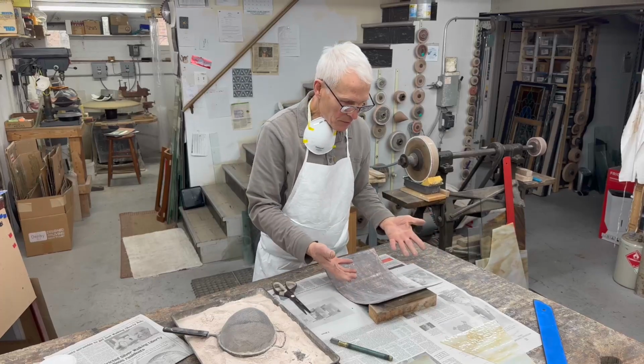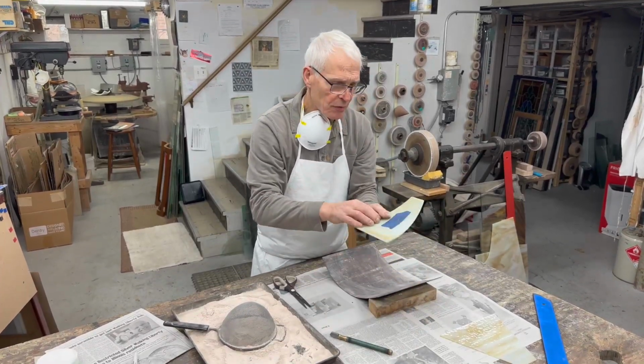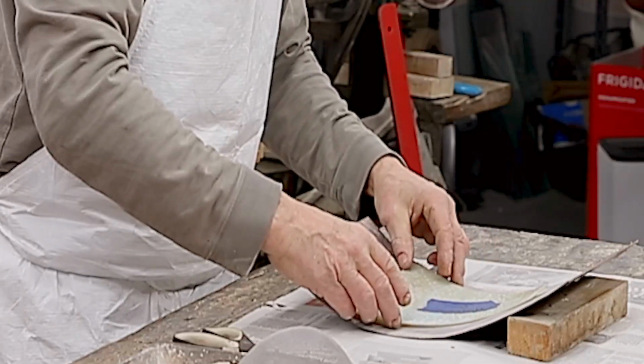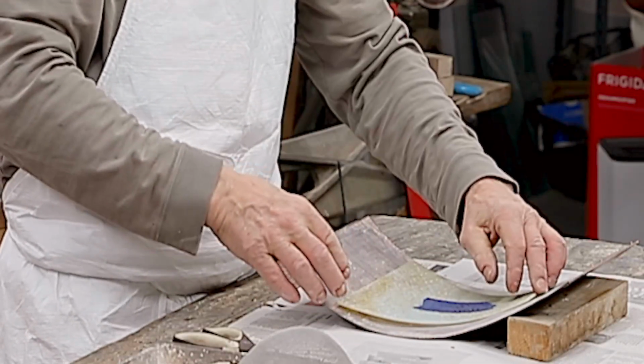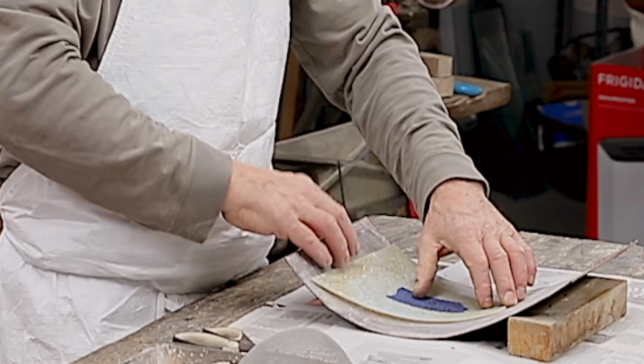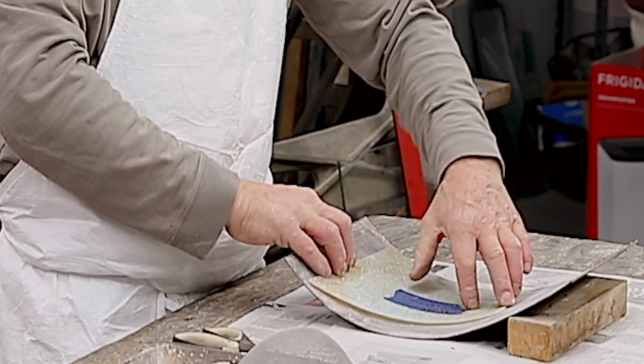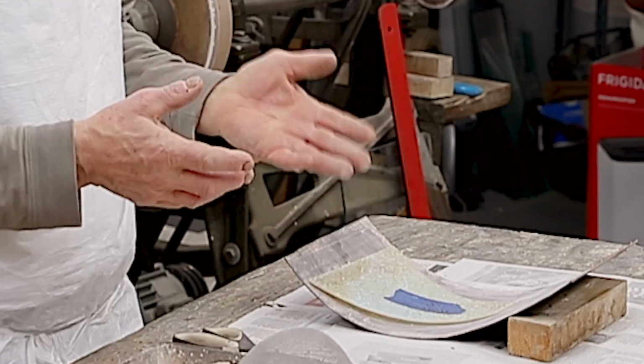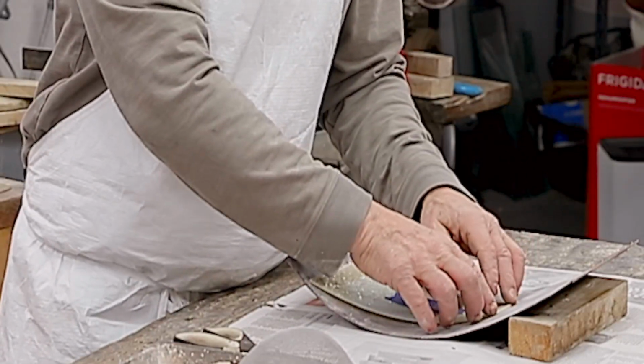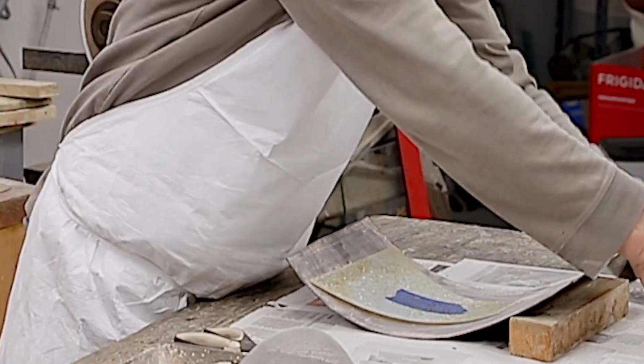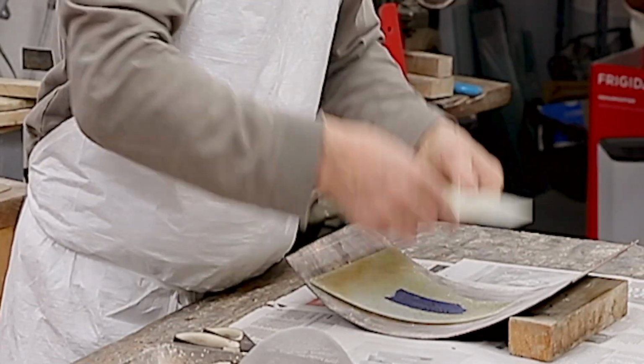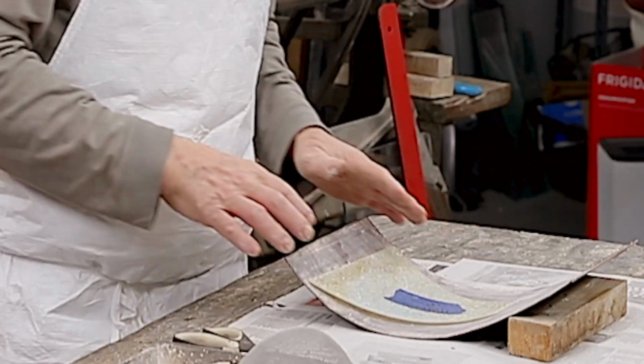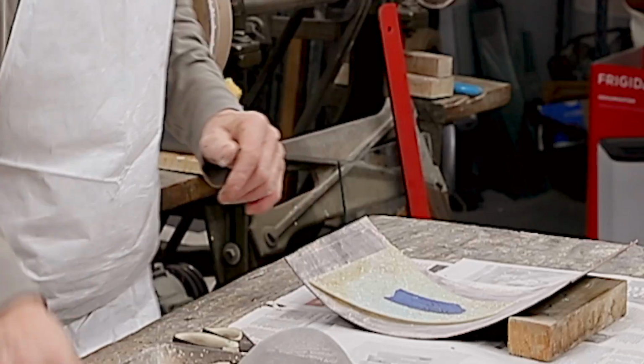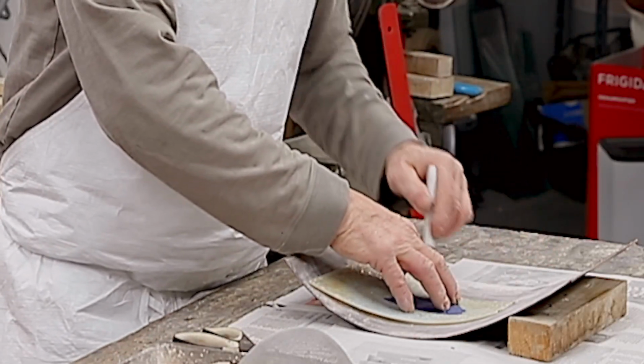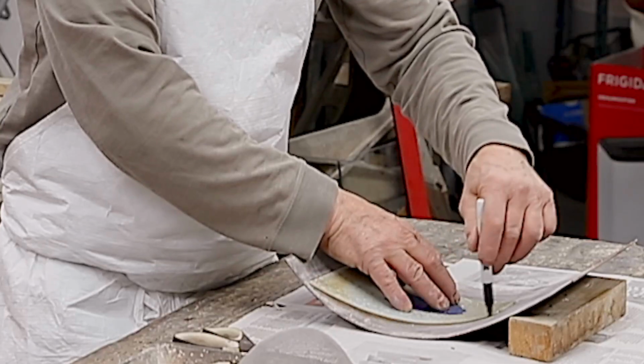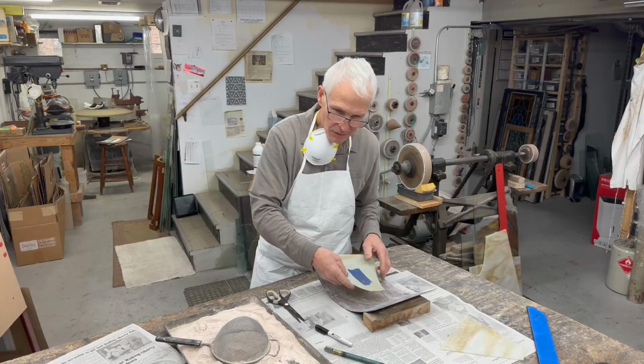The next step: we're going to take a piece of metal that's close to the contour of this and make sure that the front end and the back end are hitting the metal. Because with a powder mold, if the glass isn't touching the metal and you put your blank on the powder, it'll just sink down. So this way, there's support front and back. It will have some guidelines, and they're going to get covered up.